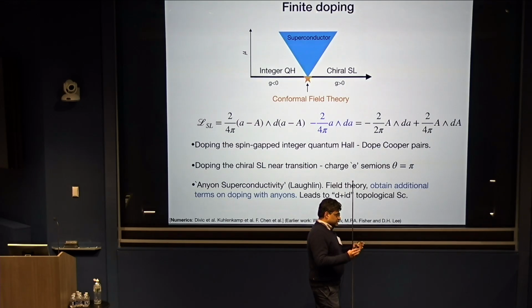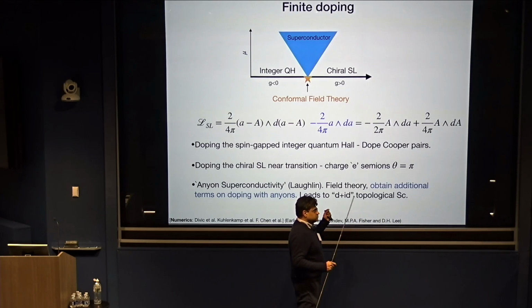And this additional flux is seen by these bosons. So doping does two things for the bosons. You change the density and you change the flux that they see. And if you look at the commensuration between the two, it's as though the bosons are at filling 2. Actually, they're at filling -2.